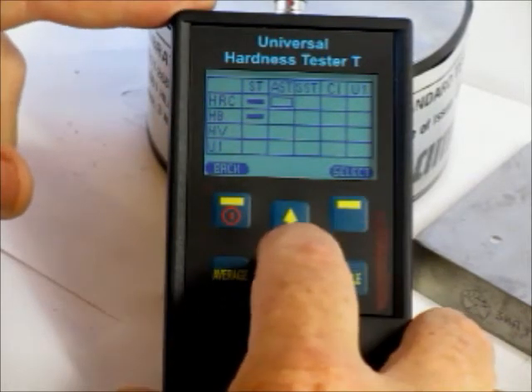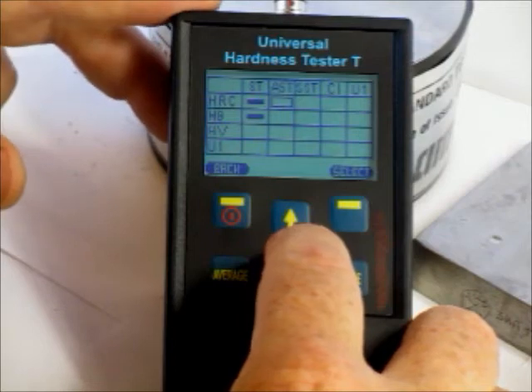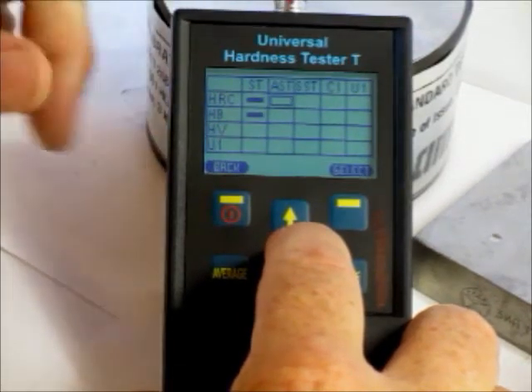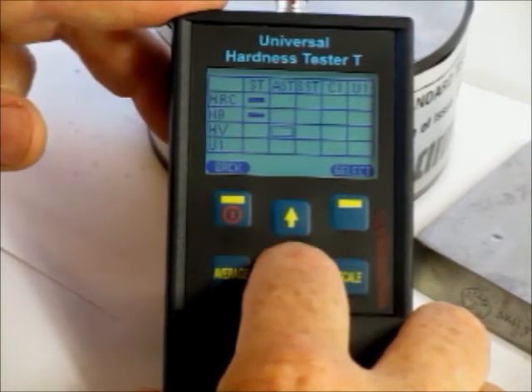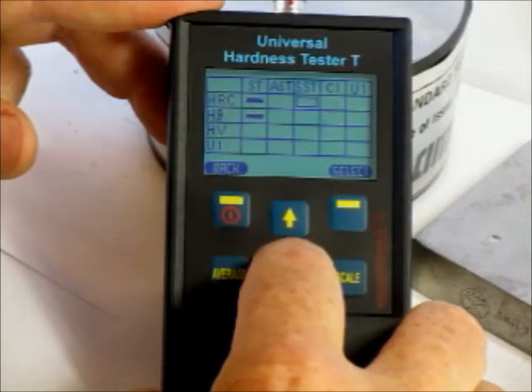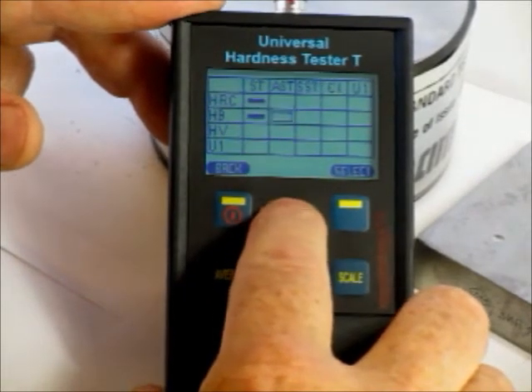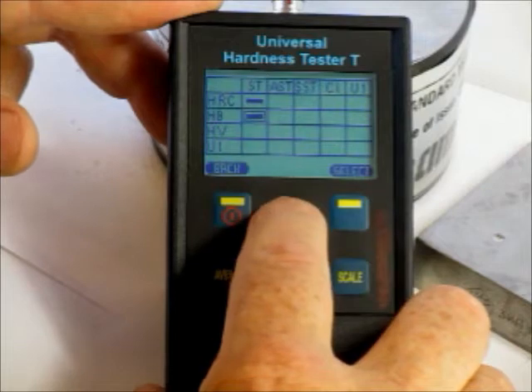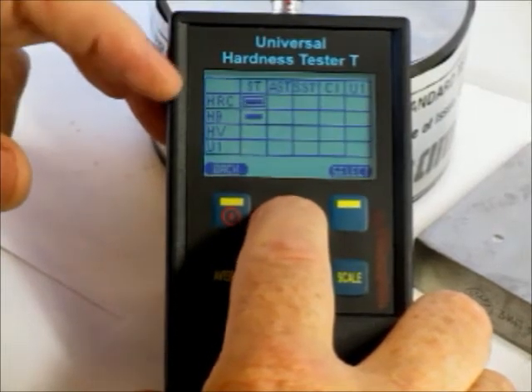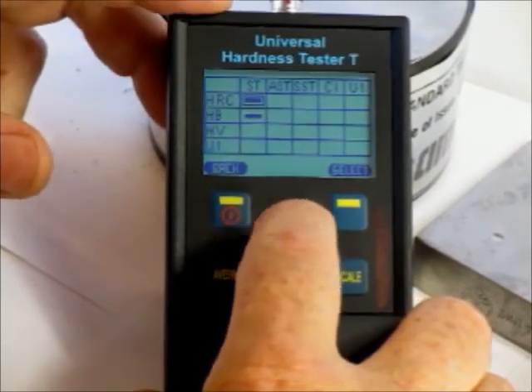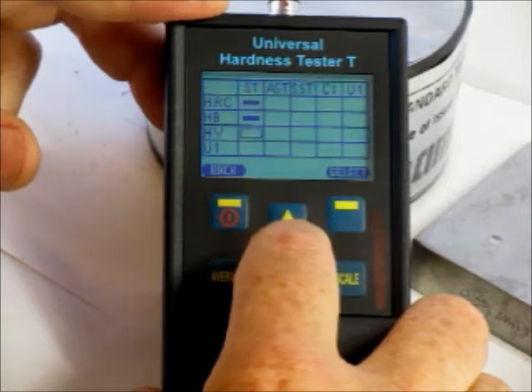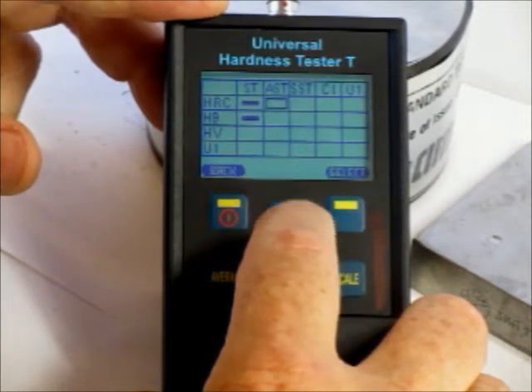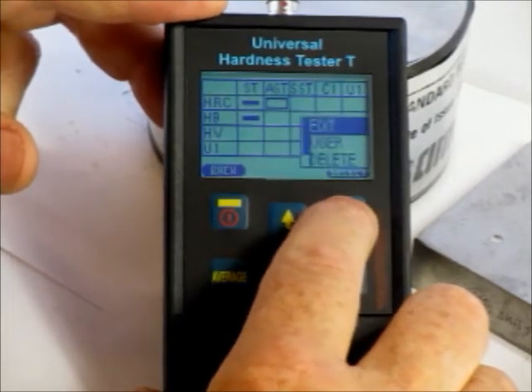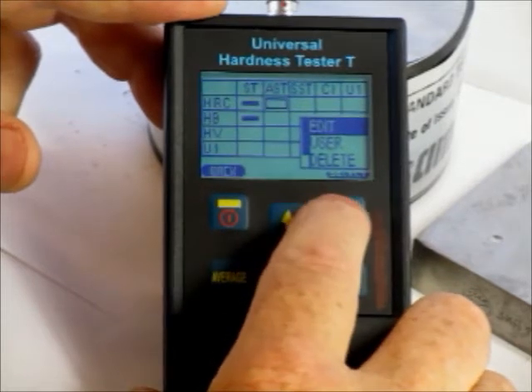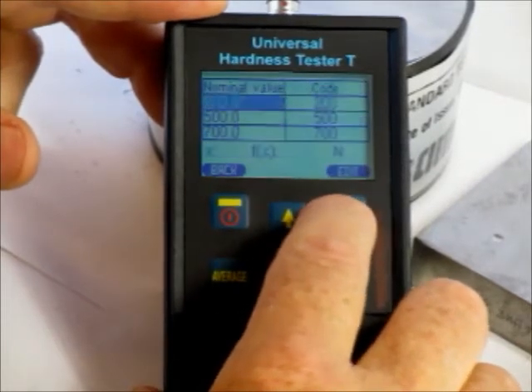What I'm going to be doing here is calibrating the unit for high carbon steel using my calibration test blocks. So you can see I can move my cursor around, and this will be choosing to create a calibration, in this case here, for steel and Rockwell C. I don't want to overwrite the current calibrations, I want to create a new one, so I go over that field and I hit select. I want to do edit, so I hit the same button again.